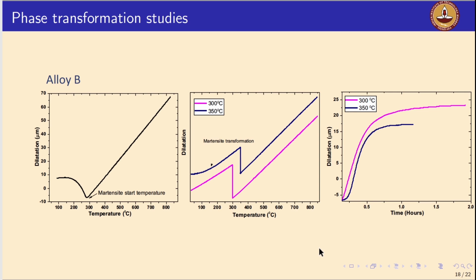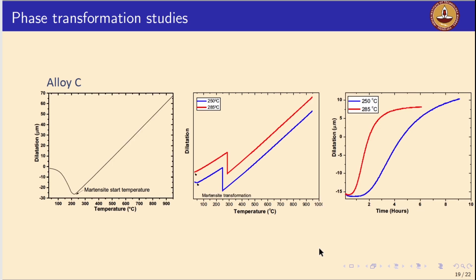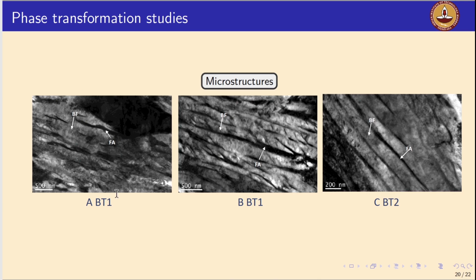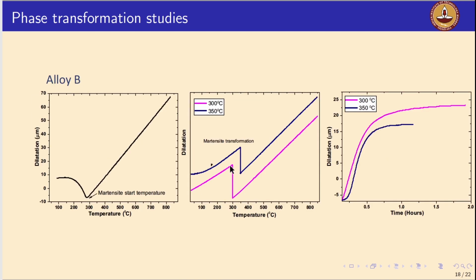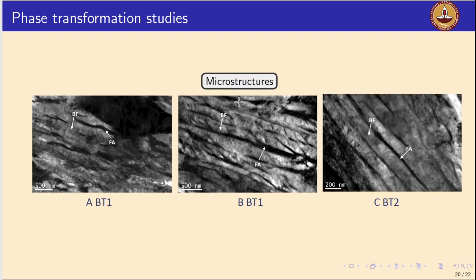Now, based on the dilatometry studies, we have also optimized the weld thermal cycles, right? So now we can happily weld, right? We have chosen the best weld thermal cycles in all three chemistries, alloy A BT1, alloy B BT1, for example. So the thermal cycle I show over here: cooling the welds until 300 degrees centigrade, then holding it isothermally for about an hour, and subsequently cooling the weld to room temperature. And by maintaining a 300 degrees centigrade interpass temperature, we can also attain the microstructure containing carbide-free bainite and retained austenite. And the microstructure we obtained looks very good, very promising.